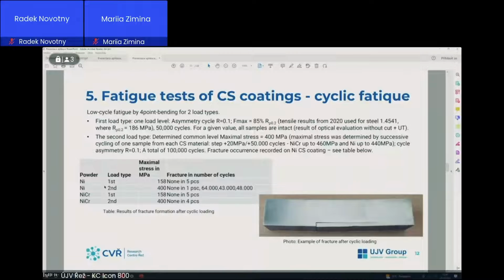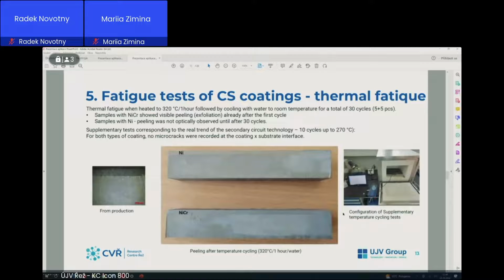With nickel, one piece was without fracture, and three pieces had fracture with this number of cycles. Here is an example of fracture after cyclic loading. As concerns thermal fatigue, samples with NiCr powder showed visible peeling already after the first cycle. Nickel coating was better. We optically observed peeling after 30 cycles.